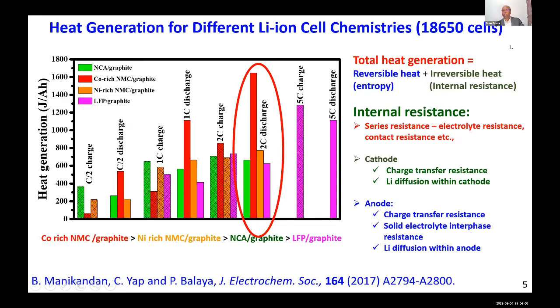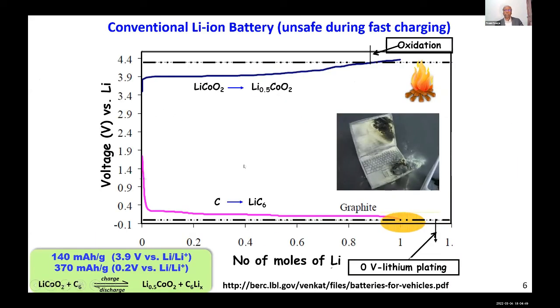That is related to so-called reversible heat and irreversible heat. Reversible heat is because you extract lithium and insert lithium. That is the so-called entropy change in the material, which you cannot help. This is chemistry specific. Whereas irreversible heat generation is mainly because of the internal resistance, so-called I squared R. R is the internal resistance. That internal resistance is caused by electrolyte resistance, contact resistance. On the cathode side, you have resistance. On the anode side, you have resistance, etc. And industries are really struggling to minimize this internal resistance as much as possible, so that one can minimize the irreversible heat, and thereby one can avoid the so-called thermal abuse. So having said this, this one is also a well-known concept.